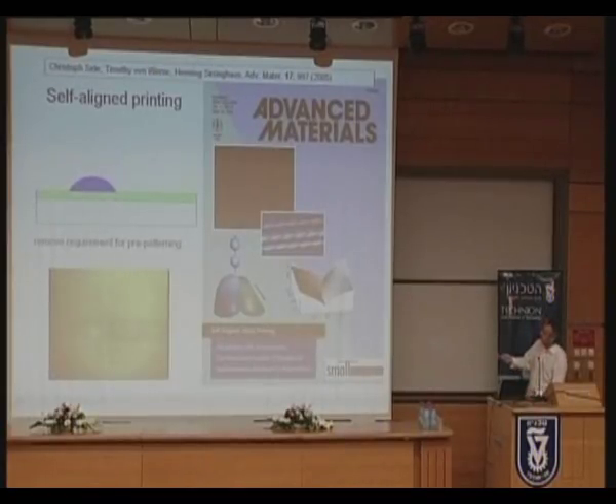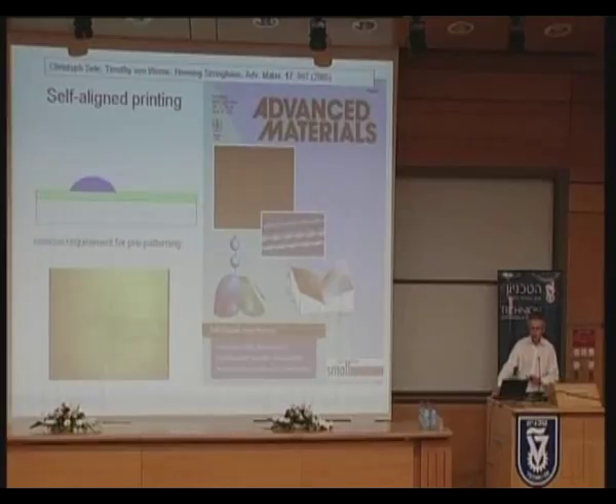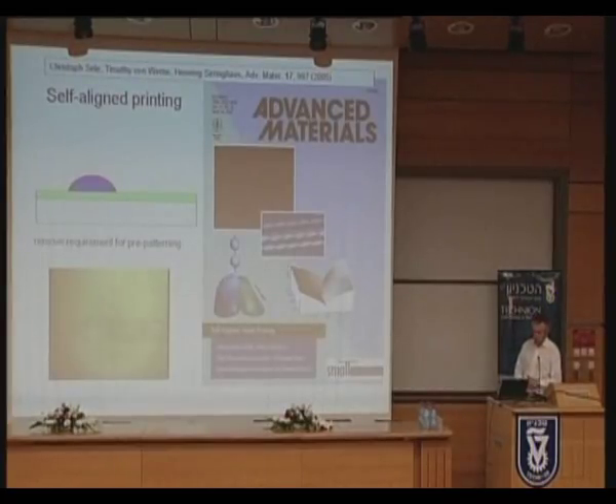So what we've done here is to print down a first drop, which may well be from a water-based solution, the PSS, and it'll have a hydrophilic surface. Now we can do some chemical modification to it to make it hydrophobic, and in brute force would be a carbon tetrafluoride plasma. More subtly, we can put a surfactant into the polymer mix when we inkjet print it, and the surfactant will end up on the top surface.